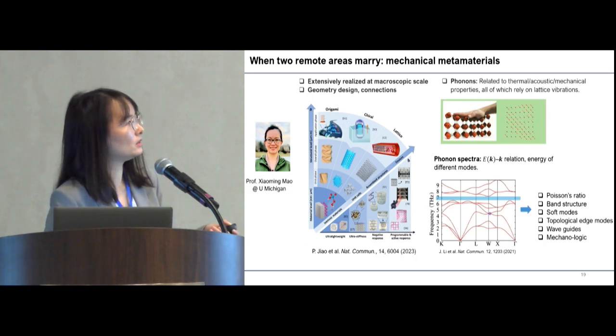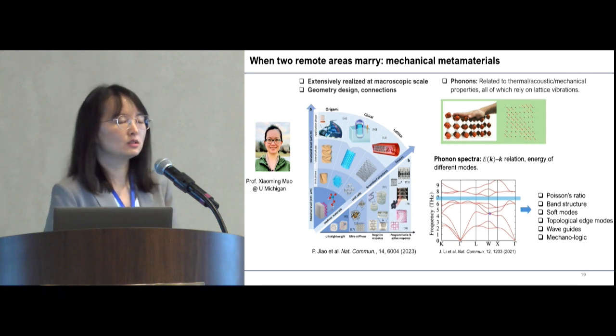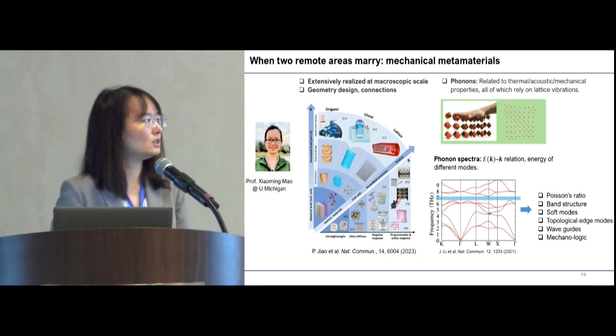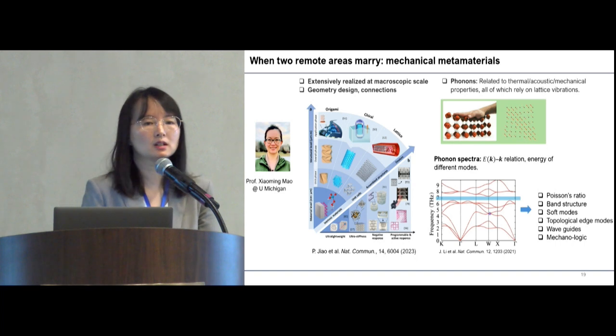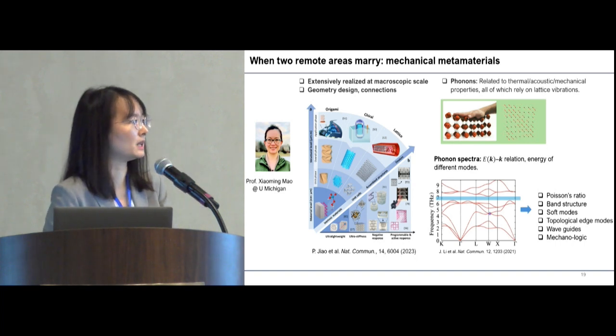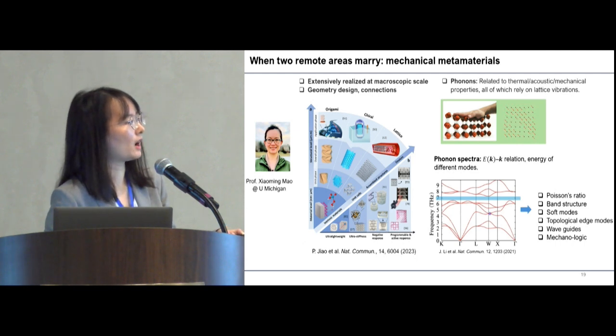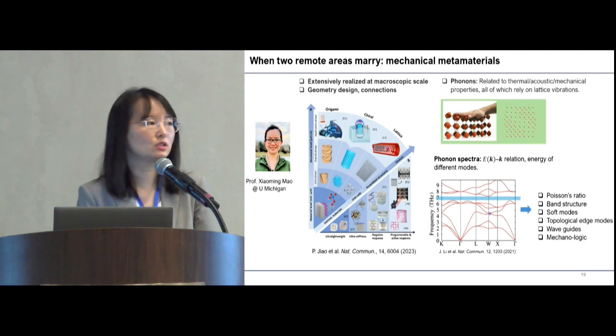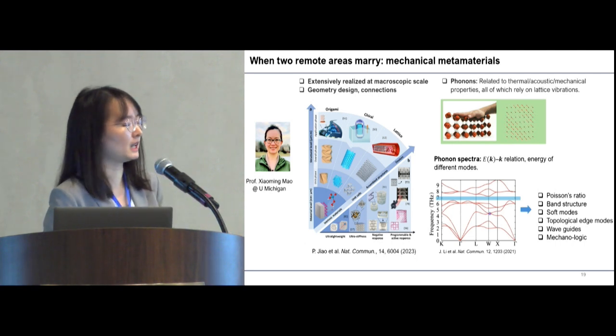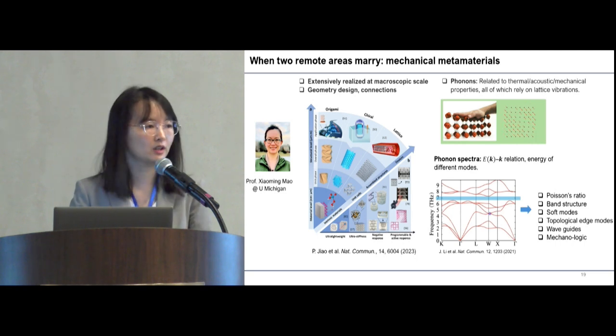And then fundamentally, this is because you can see structures as beads connected by springs. So when you agitate the structure, you will induce phonon vibrations, and that will really correspond to the mechanical response. Quantitatively, this is measured by this phonon dispersion relationship, where the x-axis is the position of the first Brillouin zone, the y-axis is the phonon frequency. So from this phonon dispersion relationship, you can basically read all the mechanical property features showing out there.